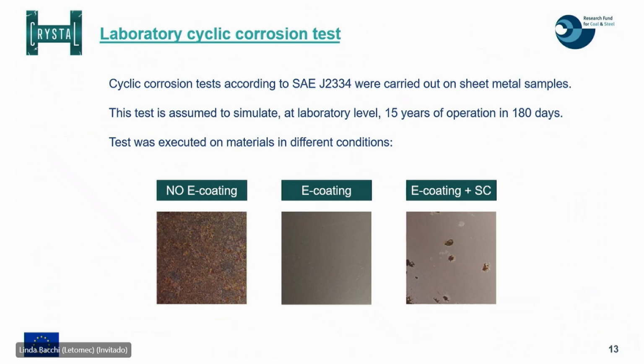On this sample that we cut, we realized for the 4 materials under investigation, we decided to test 3 different conditions. The first one was without the cataphoretic coating. The second one was with the cataphoretic coating. And then we decided to add one more condition, which was the application of the coating and then simulation by stone chipping of a sort of damage on the surface.